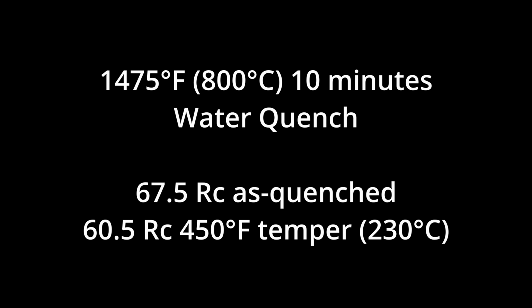So when I finally got this steel to harden properly in water, I was getting around 67.5 Rockwell as quenched. That's typical for a high carbon simple steel. And we did a 450 degree temper, which led to around 60 to 61 Rockwell. 450 degrees is a relatively high temperature. We gave it a little bit more temperature to bring down the hardness more because this is such a high carbon steel. We wanted to give it the best chance possible for the toughness test. So we tempered at 450.